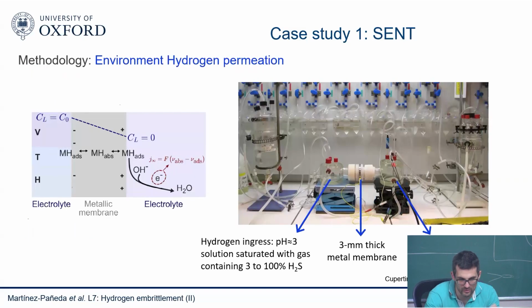So the permeation is what I explained to you on the previous day. You have an electrolyte where you have the Volmer, Heyrovsky, and Tafel reactions. Then you have an absorption of hydrogen, and then you measure basically how long the hydrogen takes to cross. You can see here, by the way, the picture of the permeation tests that were done. So you have a solution here, in this case with H2S. It's a bit more complicated solution than what we normally use in the lab. You have a membrane of your material, and then you have some sort of an oxide surface where you measure the hydrogen coming out on the other side.